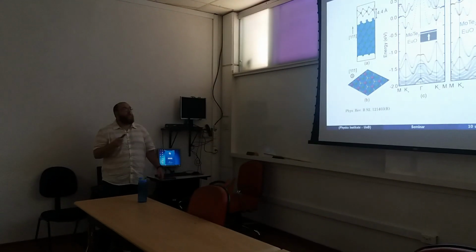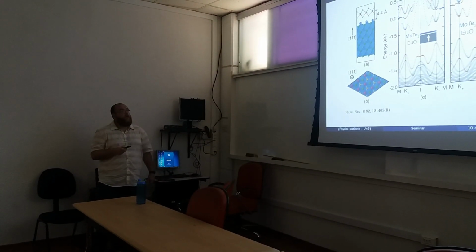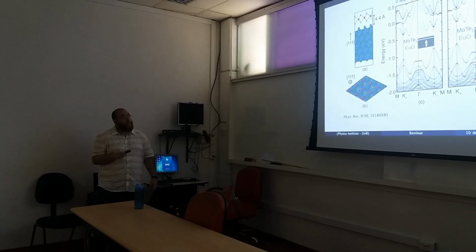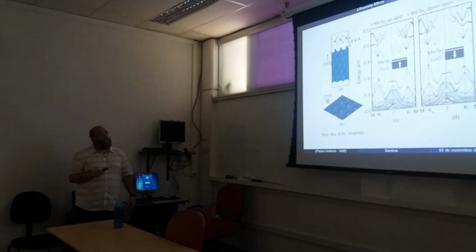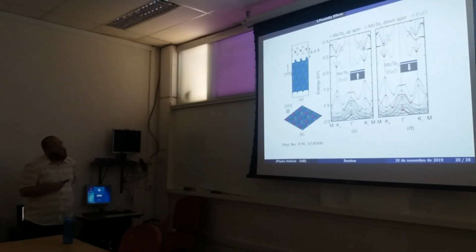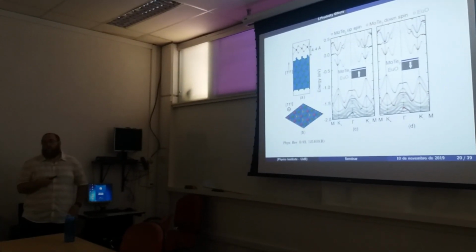But okay, you can look at the picture and tell me, okay, but it's indirect band gaps. I agree with you, but what is interesting is those indirect band gaps, because you mix the bands of the substrate and the bands of the monolayer. So this part of the indirect band gap corresponds to the oxide of europium contribution. And when I try to calculate optical properties at this distance, the probability of having an electron here and a hole here is very, very small.